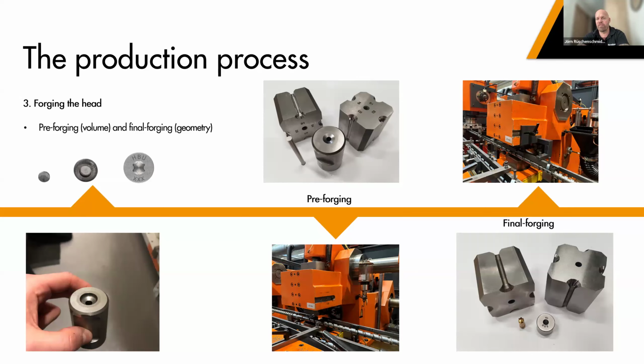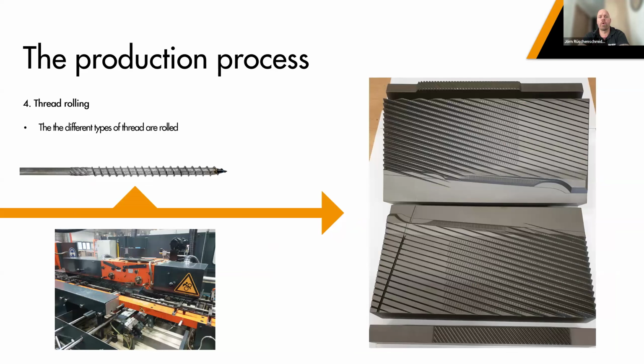This is called the pre-forging, done by a special die, which grabs the screw from the side. The round cavity covers the top, and then a little pin shoots through the hole and makes the first geometry. In the final forging, you see the die is a bit more detailed for the milling ribs and more details. So the die grabs the now pre-forged screw from the sides. The little piece comes on top, and then the pin with the Torx drive punches in and forges in the drive. Next step, we normally roll the thread.